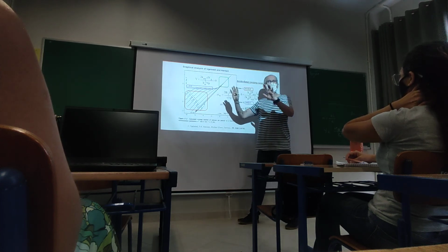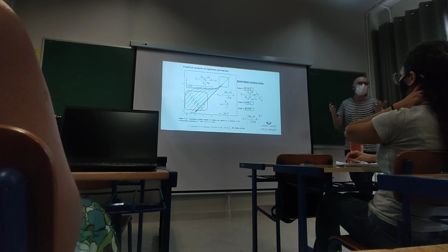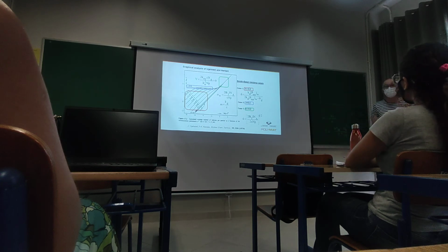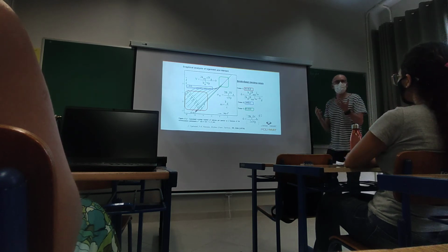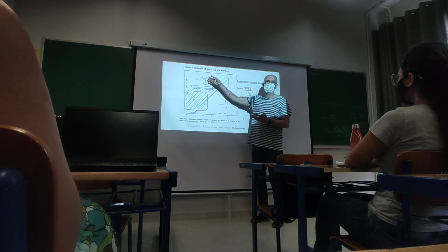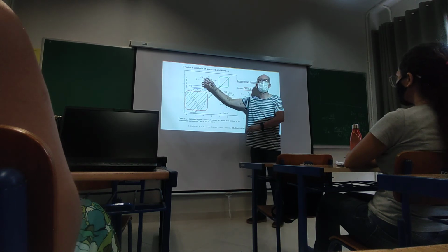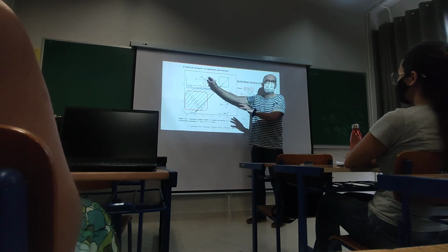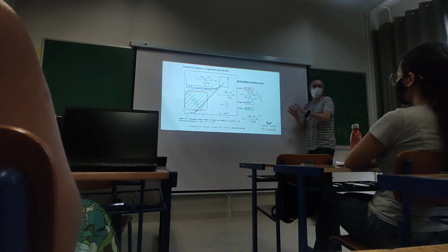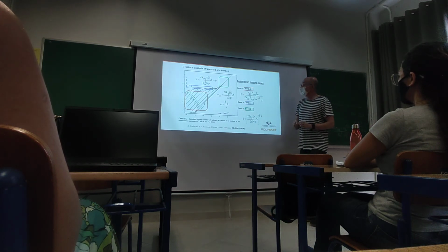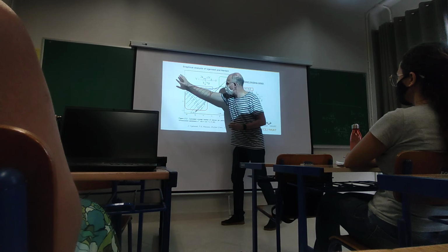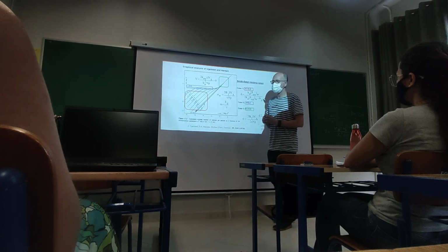Okay? So this is a case which is very classical for instance, very hydrophobic monomer, styrene. Not for vinyl acetate. For vinyl acetate, termination in the aqueous phase will be important, as we have seen. But for styrene, this holds very well. Styrene and hydrophobic monomers.